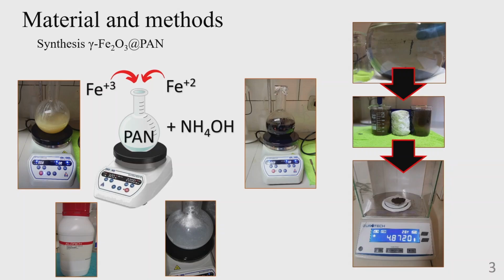Then we prepared a suspension in 48 milliliters of ethanol and 12 milliliters of ultrapure water. The resultant solution was sonicated for 30 minutes, and the pH value of the solution was adjusted to 11 with ammonium hydroxide.